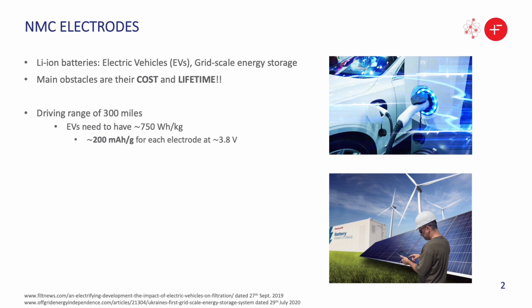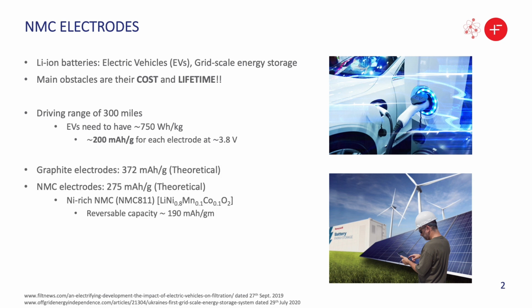Currently, battery manufacturers lack information about the aging of lithium-ion batteries at different climate and operating conditions. So degradation studies are important, and specifically degradation of the positive electrode is still at a very novice stage. Let's take an example of an electric vehicle with a driving range of 300 miles. For that, one needs lithium-ion batteries with a specific energy of 750 watt hour per kg. That means around 200 milliamp hour per gram for each electrode, if each electrode operates at an average of 3.8 volts.